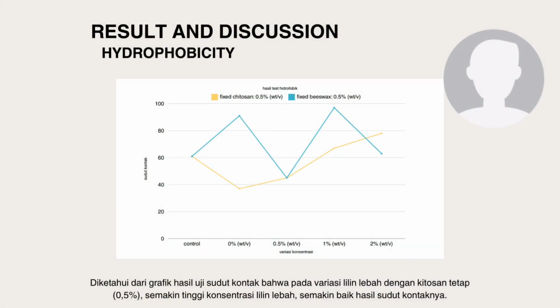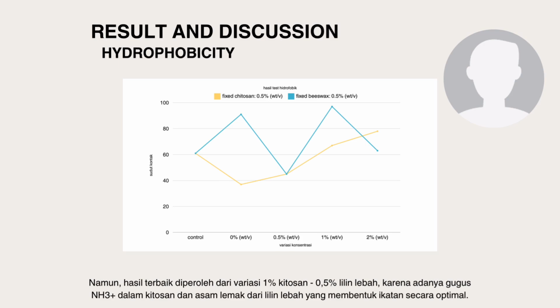For the results and discussion, first there is hydrophobicity. It is known from the graph of the contact angle test results that in the variation of beeswax with fixed chitosan 0.5%, the higher the concentration of beeswax, the better the contact angle result. But the best results obtained are from the variation of 1% chitosan and 0.5% beeswax, due to the NH3+ groups in chitosan and fatty acid from beeswax forming bonds optimally.